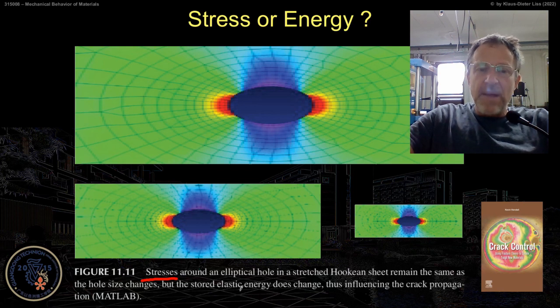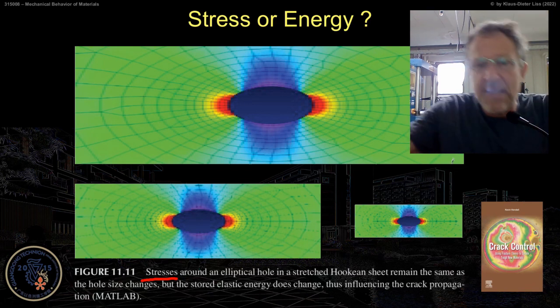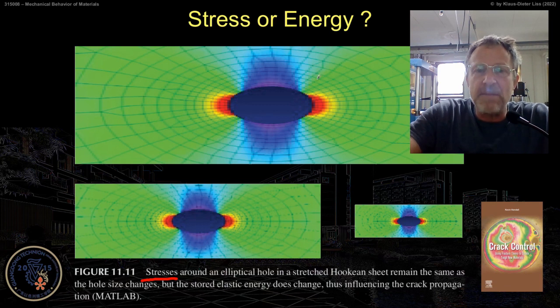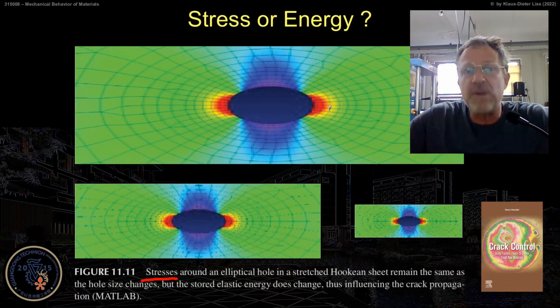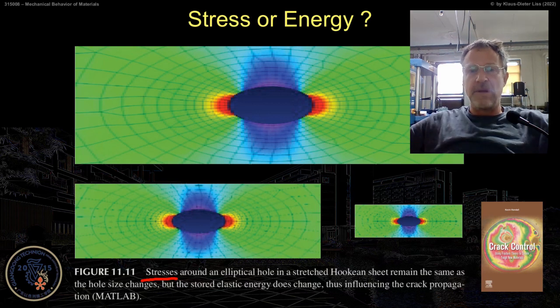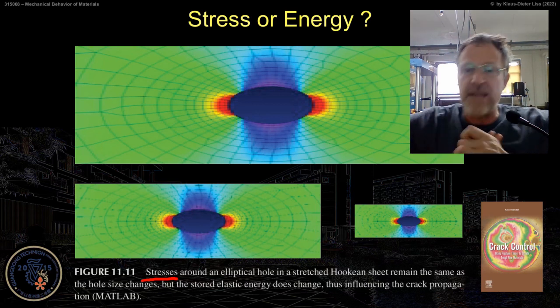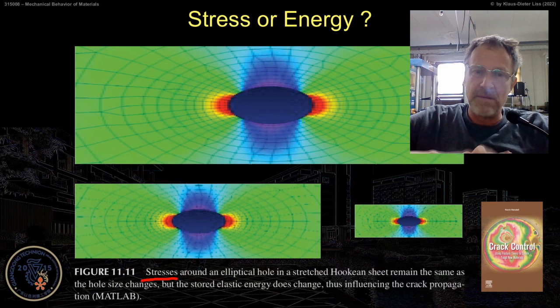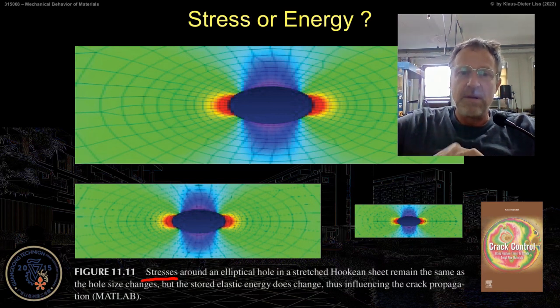But the stored elastic energy does not change in the same way. There's different stored elastic energy because the stress field in a big ellipse is much larger than in a small ellipse. The release of that stress field and the stored energy can make much more damage than in the small one. So that's why it would not scale in an experiment with just A over B.